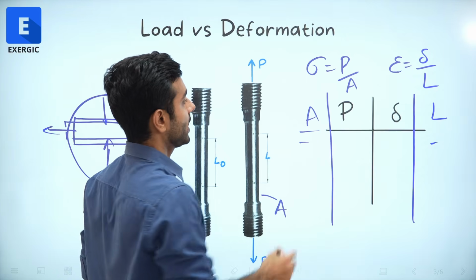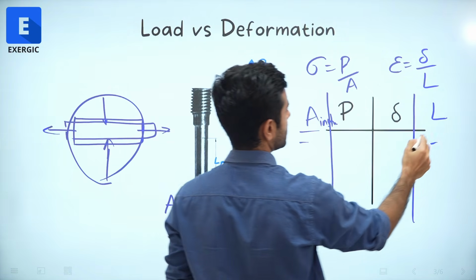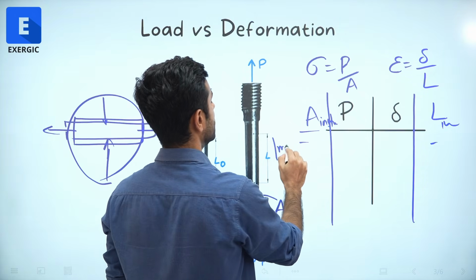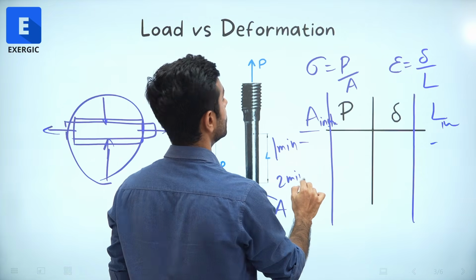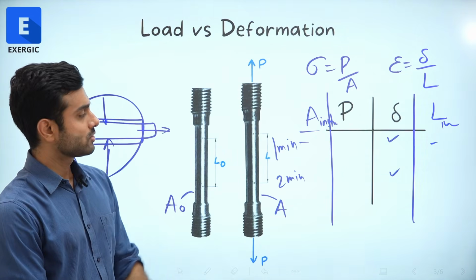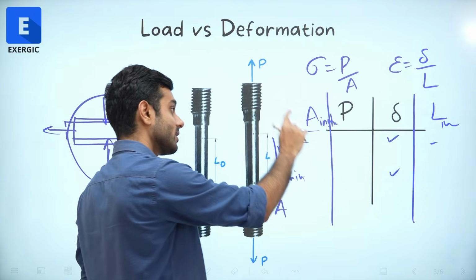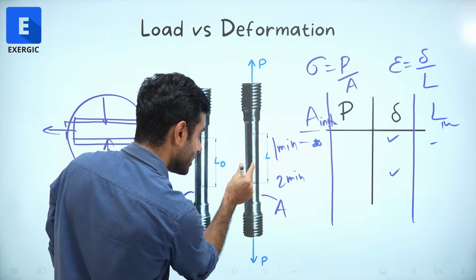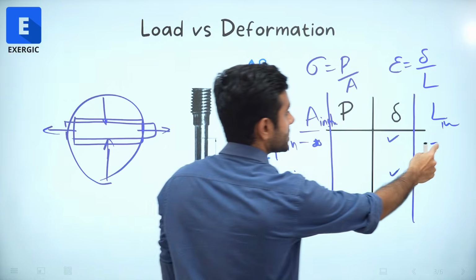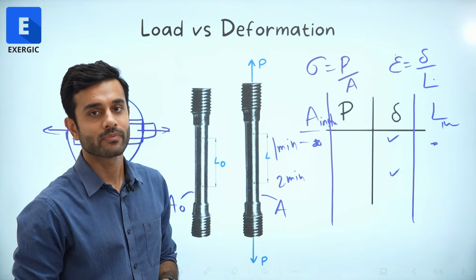So to find out the stress, I will use the actual instantaneous area, instantaneous length. At that instant, as I told you, after every few seconds or few minutes we are taking a reading such that the value of del is increasing at a uniform rate. So in every reading, the true scientist is using whatever the area is. He is measuring the diameter, from that calculating the area, and measuring the length, which he puts here to find out the strain at that point of time.